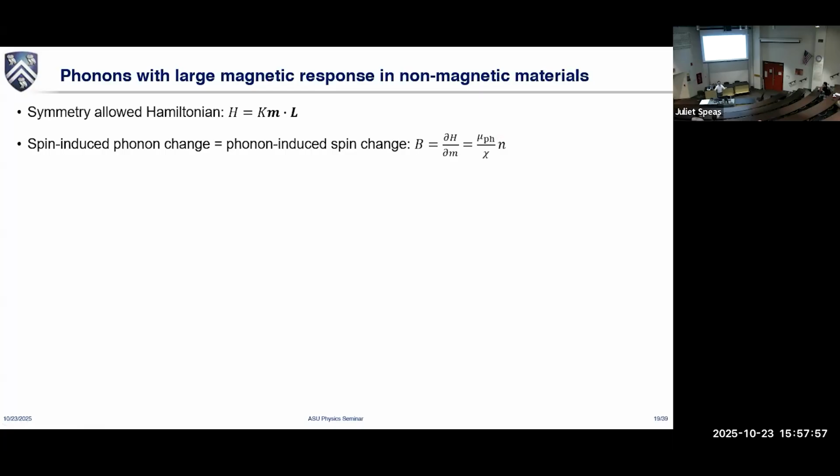You would imagine that these are ionic motions, right? So if you have an ion that rotates, and these are quantized, phonons are quantized, and because they're very heavy, their magnetic moment should be pretty small compared with the electronic magnetic moment. Just as if you look at the nuclear magnetic moment, it's 3 orders of magnitude smaller because of the mass than the electron magnetic moment. However,